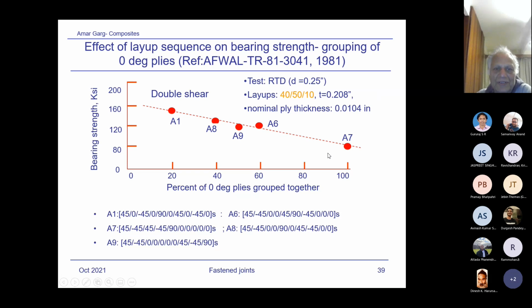But the purpose of this one is to demonstrate that when you're designing, the layup sequence is very important. You may have the same number of 0-degree plies, the same number of 45s, and the same 90s, but the way you arrange them in the laminate is very important. This is what I'm trying to say. So the message is never club or bunch the plies of the same orientation together. Like you are seeing in A9, A7, bunching of all the plies together, like 0 degrees all bunched together. So this is the lowest strength compared to when the plies of zeros are staggered. So this is the highest strength, and that has the lowest, almost 50% strength.